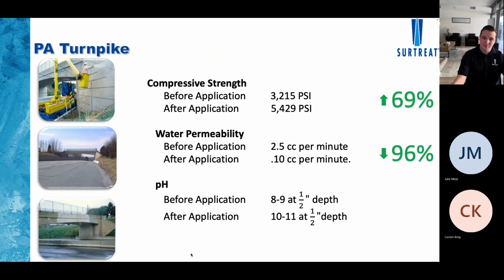Now, a little bit of the same story with the Turnpike. We're a Pennsylvania company, and we have history with the Turnpike and with PennDOT. I'll show you a couple cases from the Turnpike and a case from PennDOT. This bridge was done as a demonstration just to show the impact of what Surtreat could do. I like this picture a lot at the bottom because we started installing the Surtreat, which again reduces the porosity and the water permeability, and then it started raining, so we had to stop. The next morning we came back, and as you can see, the area that was treated with Surtreat is virtually dry. No water was able to penetrate, whereas the areas that were not treated obviously have a big change in color.